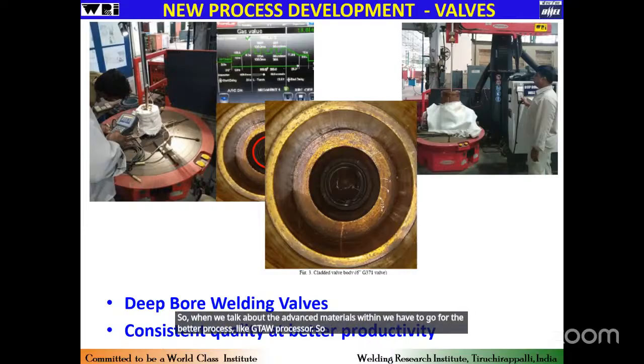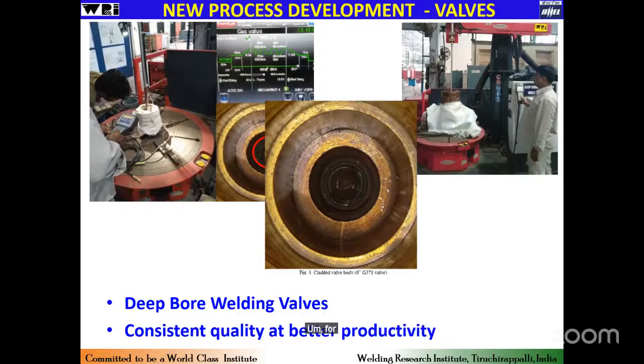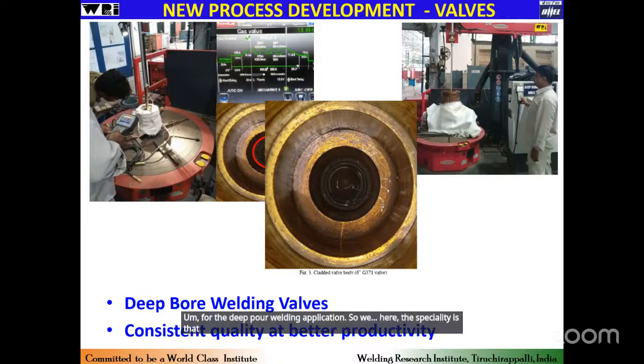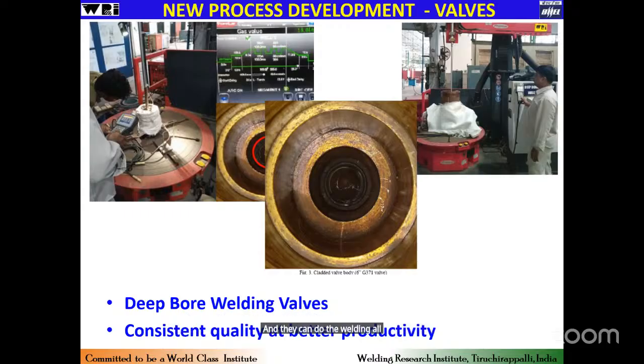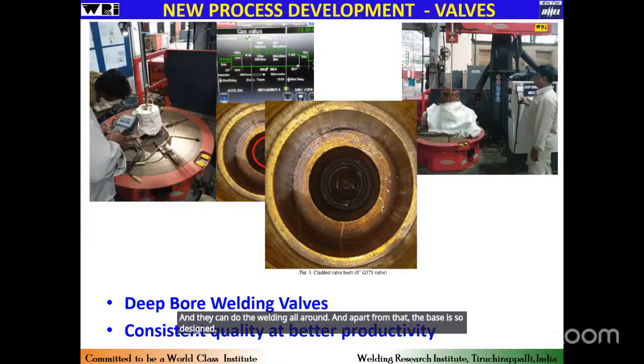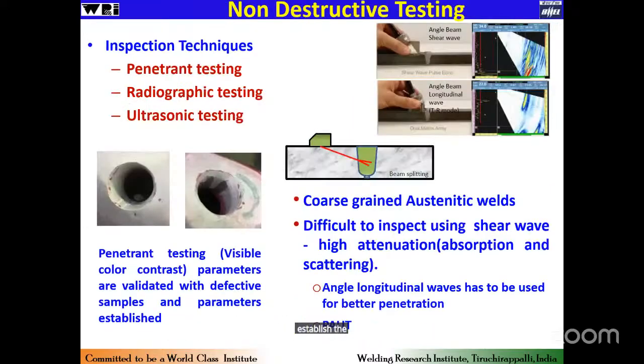So when we talk about advanced materials, we have to go for a better process like the GTAW process. One such special purpose machine has been developed with the support of Fronius India for deep bore welding applications. The specialty is that it has a narrow torch which can go into a depth in excess of 600 and do the welding all around. And apart from that, the base is designed so that it can preheat the component by resistance preheating as well. That has been optimized, and we could establish the process without any welding defects.